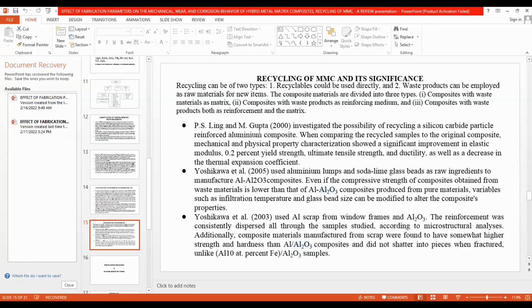So these are some of the research works carried out. P.S. Ling and M. Gupta investigated the possibility of recycling a silicon carbide particle reinforced aluminum composite, and it was found that there was a significant improvement in the ultimate tensile strength. Even the ductility and other mechanical properties were found to be significantly increased.